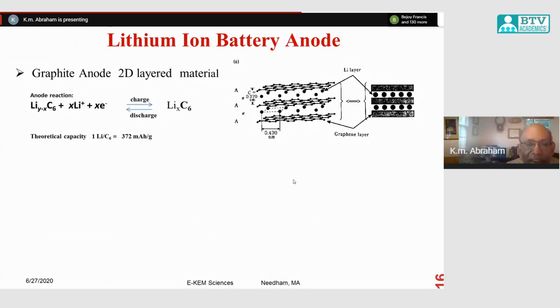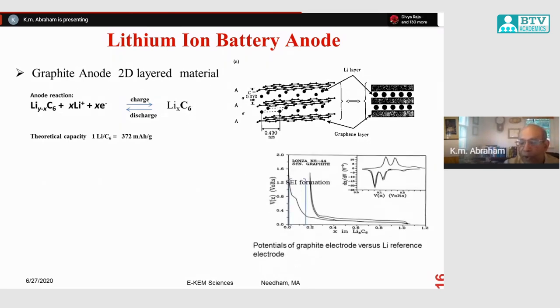So this is a graphite anode here. I want to talk a little bit about the chemistry of each of these electrodes, which is very important. As I said before, you have a graphite anode. When you charge your battery, lithium goes into the interlayer spacing in the graphite structure, and you form a lithiated graphite. That is what happens when you charge your battery. You can study that separately by making what we call a half cell with a graphite electrode and a lithium counter electrode.